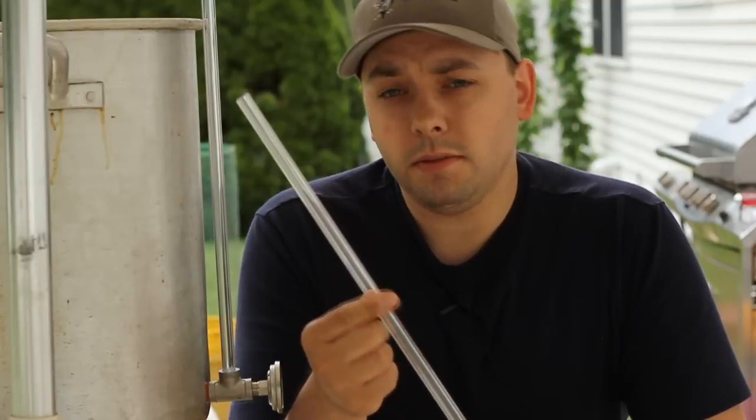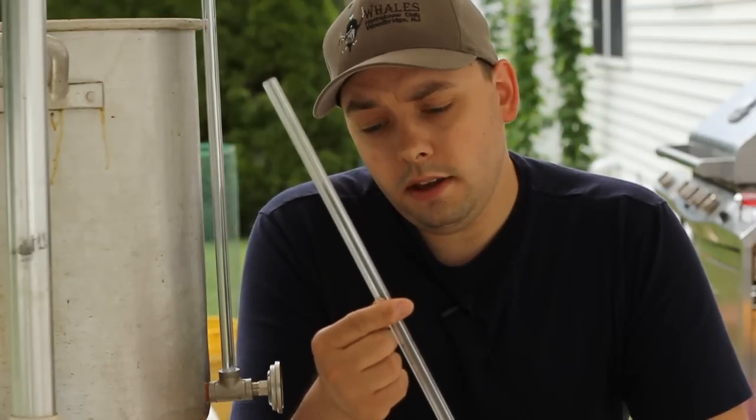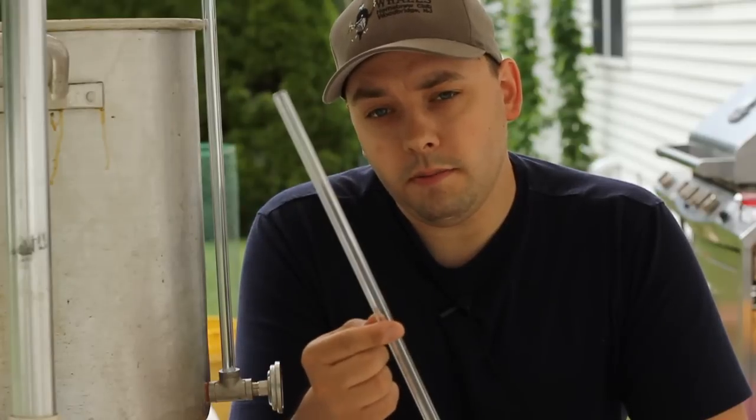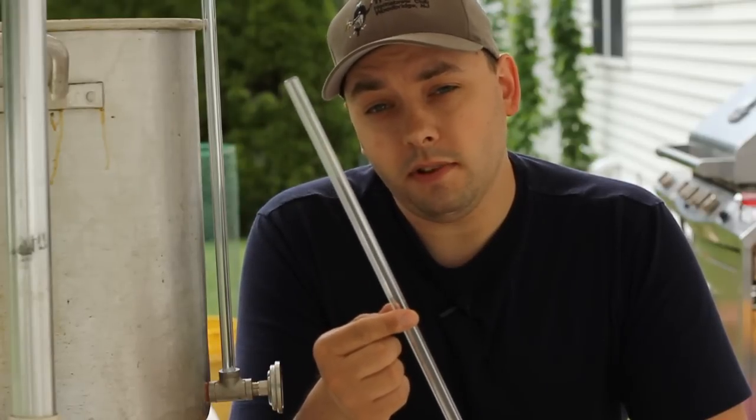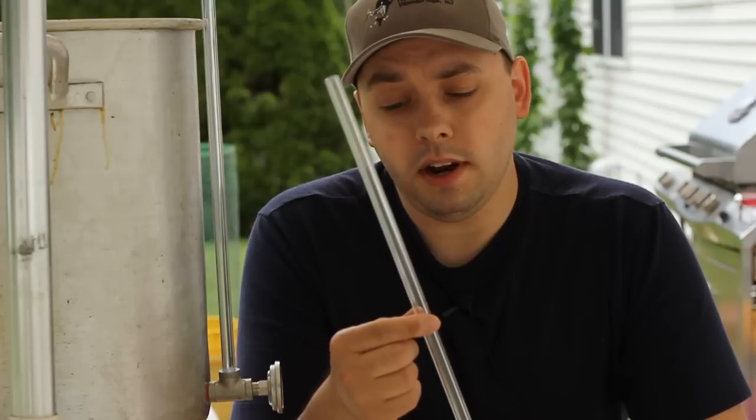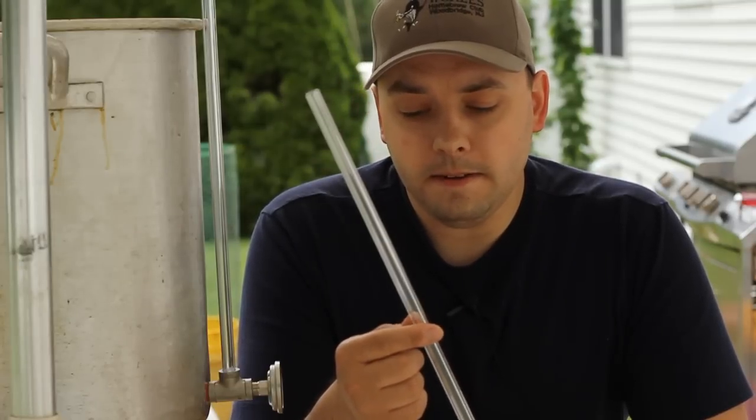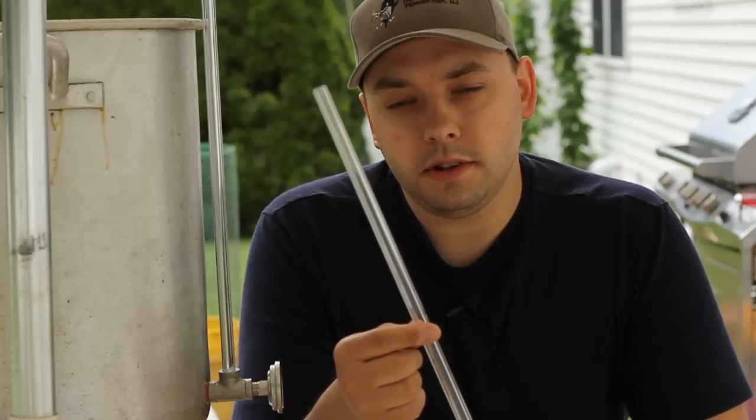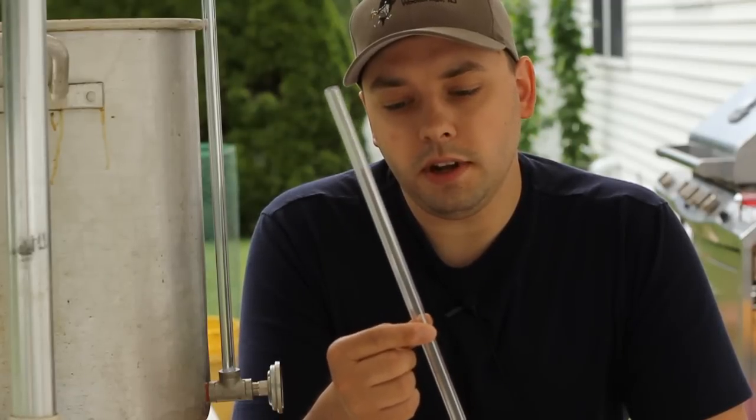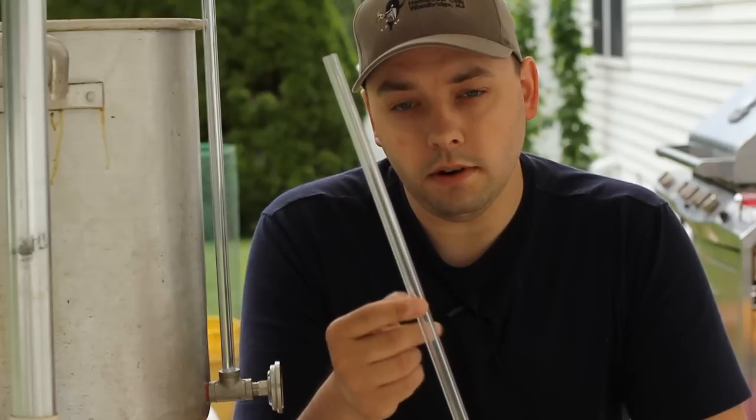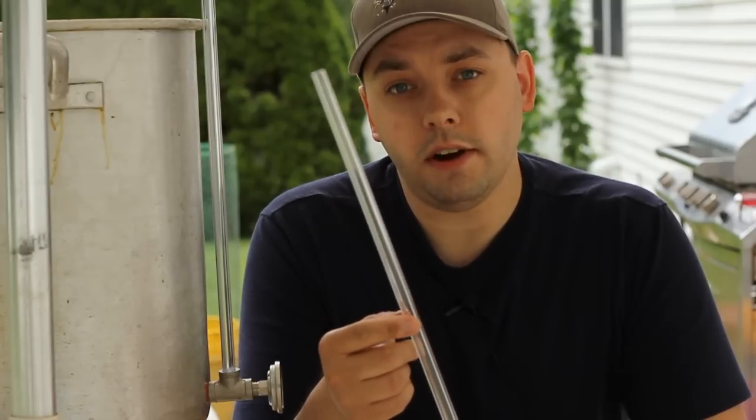But let's talk about the usable temperatures. The long-term safe temperature range or max temp for these tubes are around 225 to 250 degrees Fahrenheit. You could hit temperatures in that range consistently, and there won't be any long-term damage to the tubing or any problems with clarity.